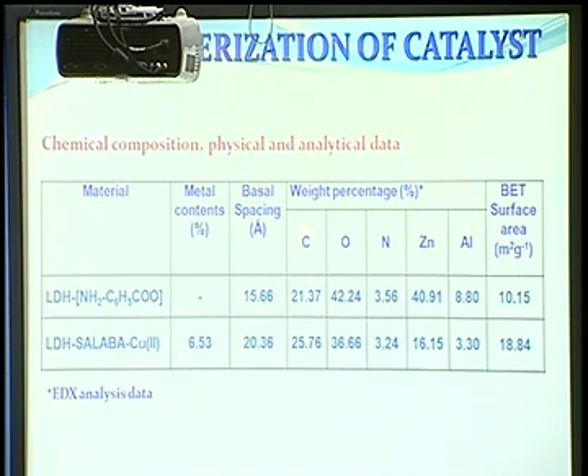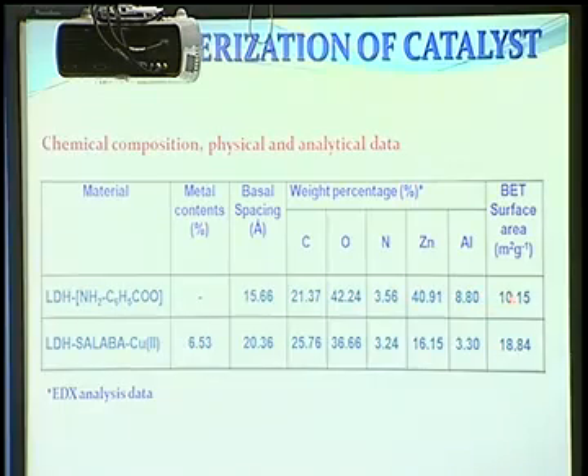Now these are the characterizations of the catalyst, in which metal content has been found out by ICP-AES analysis, and it is found to be 6.53. The basal spacing is 15.66 in my support, while in my catalyst it is 20.36 angstrom. And these are the data of elemental analysis. If we talk about BET surface area, then the support has 10.15 meter square per gram of surface area, which increases to 18.84 in my catalyst.